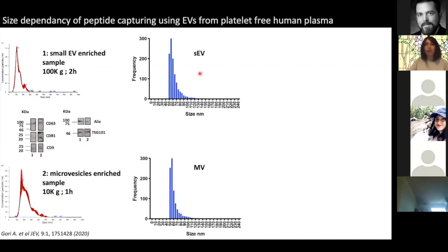You see that the size distribution of these two samples is basically the same. It's very, very similar, with the preferential binding for the small vesicles from 50 to 100 or maybe 120 nanometers. This suggests that no matter if you have a small EV enriched sample or a microvesicle enriched sample, what the peptides on the surface captured are only the small EVs.